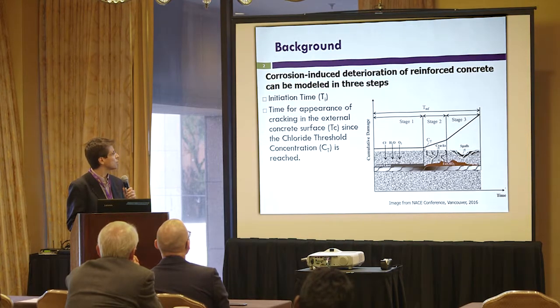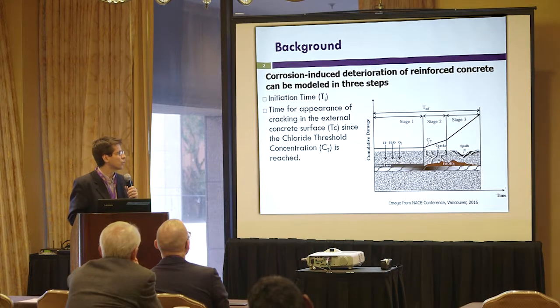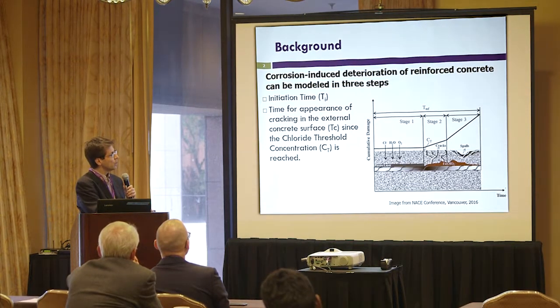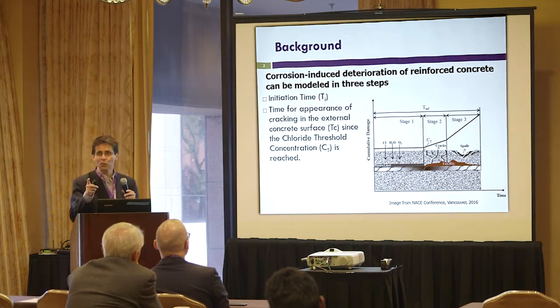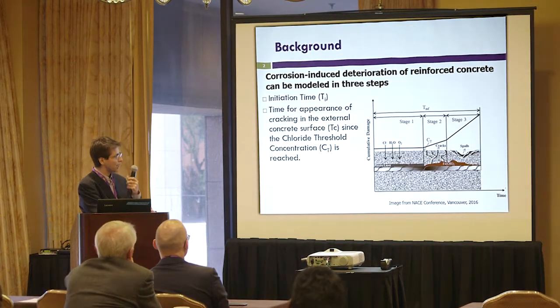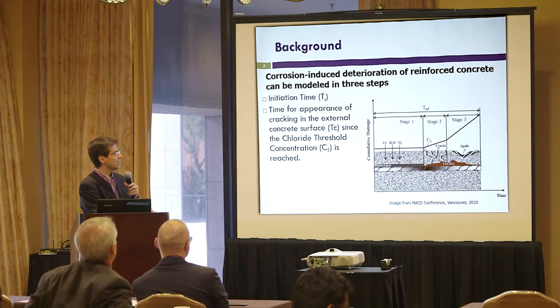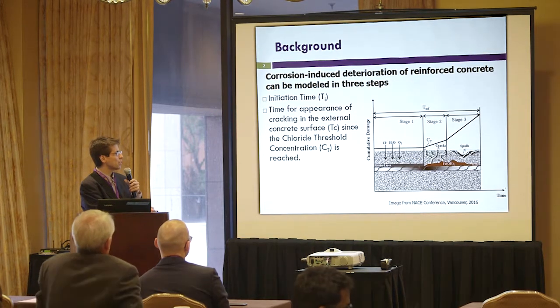Before going into the details of the self-healing and the microcapsule, this diagram illustrates very well what corrosion means in rebar-reinforced structures. The rebar we call the working electrode in corrosion — the thing that is going to corrode — and the concrete we call the electrolyte. Together, we have a composite that comprises this working electrode and the electrolyte, and the important part in corrosion is the interface.